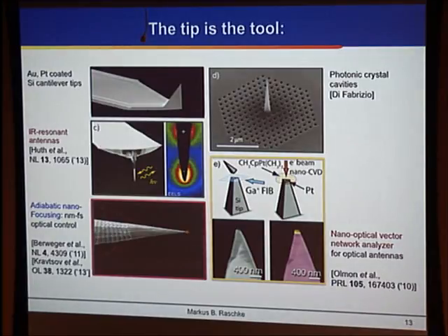And then you can also control, by appropriate engineering, a number of polarization states, and you can then build even what you could imagine as a nano-optical vector network analyzer, where you probe the in-plane and out-of-plane electric field distribution around photonic nanostructures for optical antenna studies, and really do the optical analog of a vector network analyzer, because we can reconstruct phase and amplitude of the light field.